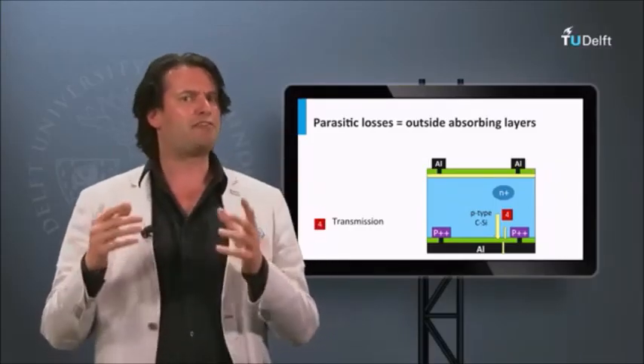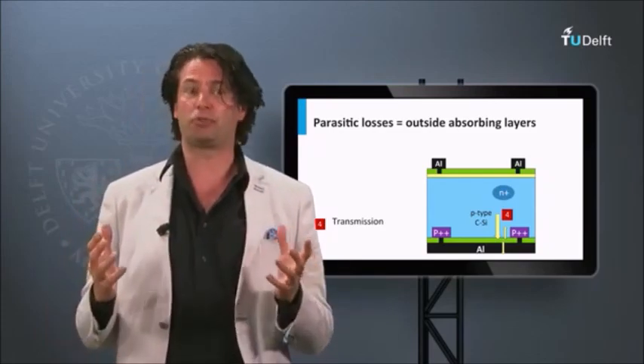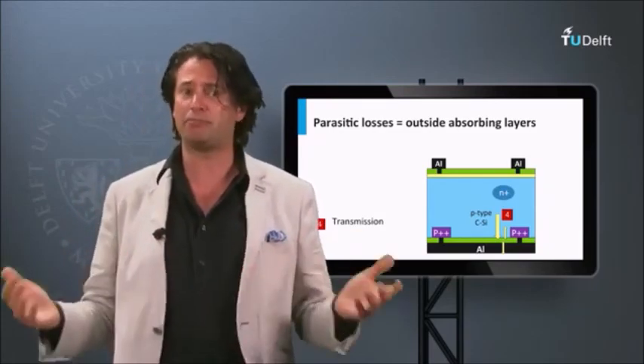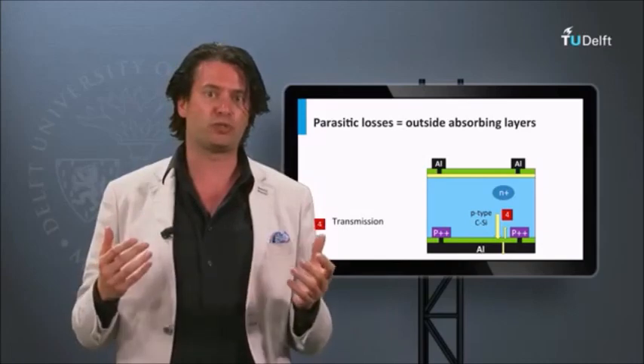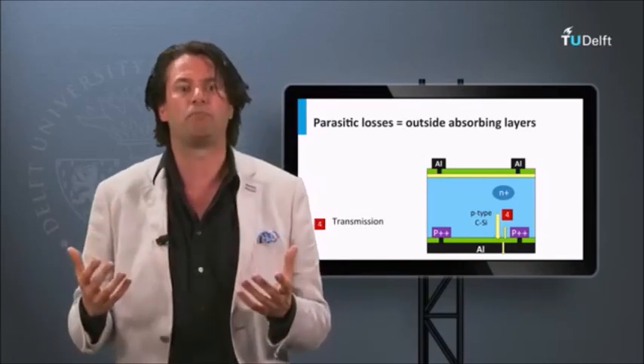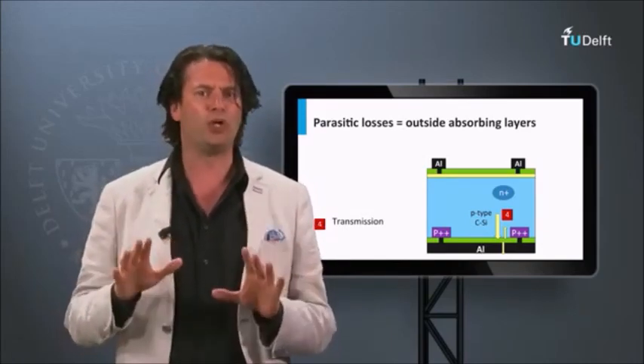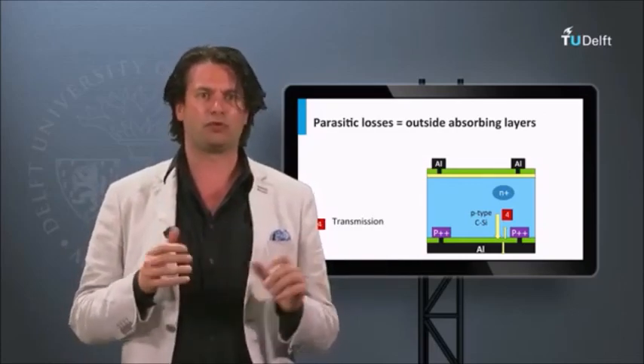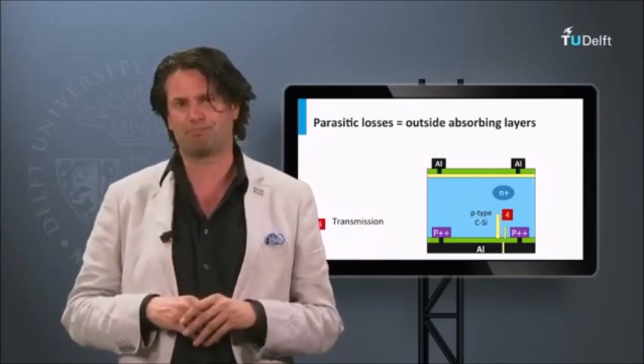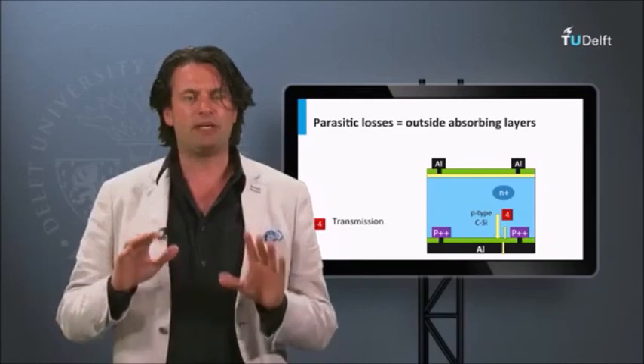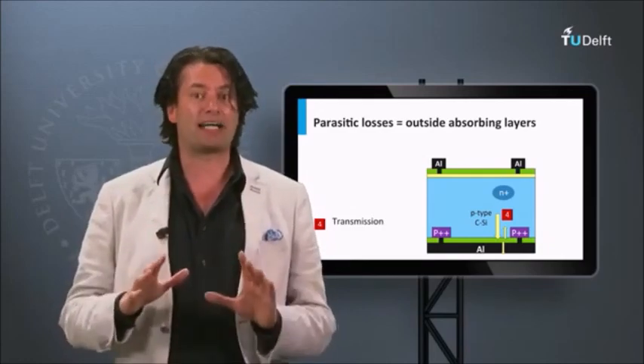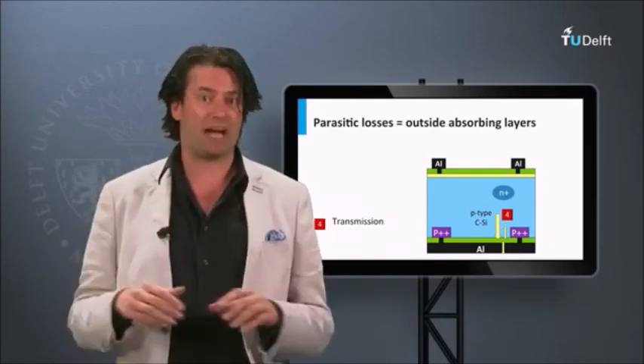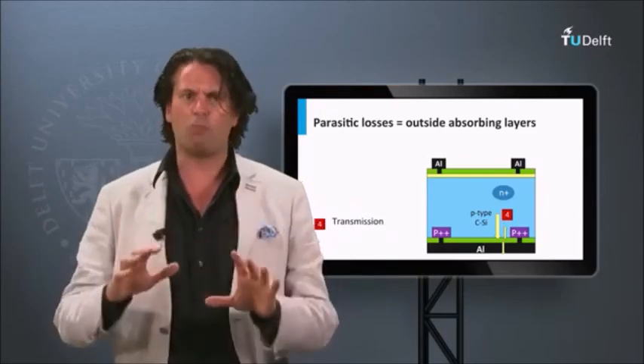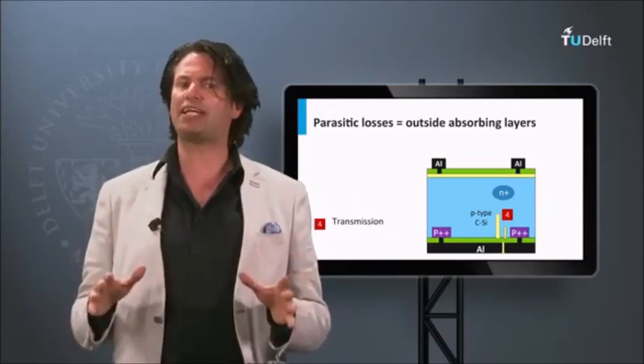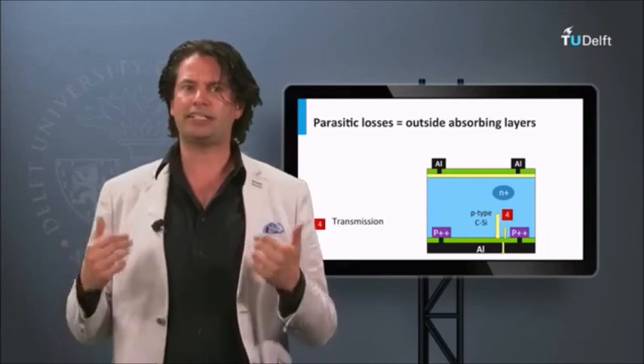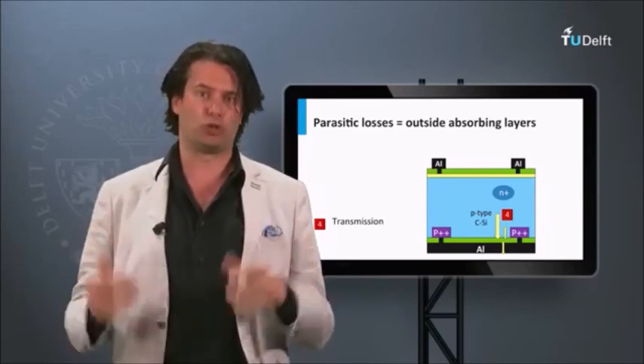Secondly, if the absorber layer is not thick enough to absorb all the light, part of the light will be transmitted. As the absorption coefficients are larger in the blue spectral part, this usually plays a role in the red to infrared part of the solar spectrum. The light transmitted can be reflected back, which is a so-called back reflector. Some of the light can also be absorbed at the back contact. This can again be considered as a parasitic absorption loss.